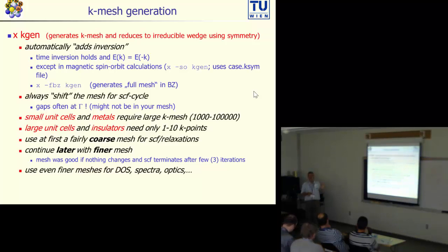It depends a lot on the specific property. I mean, this optics example for aluminum will be something where you really need a huge K-mesh. Or if you do NMR for metals, you need, as I said, millions of K-points eventually. For some other properties, it's no problem at all. You can do silicon, which also has only 2 atoms, structure optimizations with 1 K-point almost. Doesn't matter. Yeah? Of course, your density of states with 1 K-point will not look nice, right?